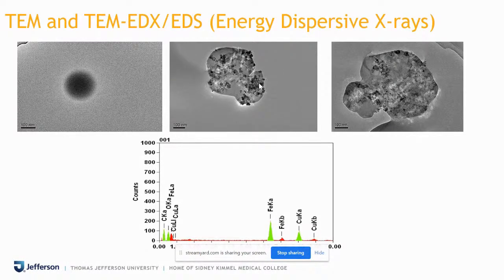nanoparticles that we synthesized. So you see over here on the left hand side, you have the nanoparticle structure, which is like a black colored ball, and it doesn't have any contrast in it. Whereas on the right hand side, the two images that you see show a polymeric shell that is covering gray colored contrasting small crystals. Now, we thought that these nanocrystals, the black contrasting dots, were nanoparticles encapsulated in the polymeric shell. Now, to confirm this, because we were